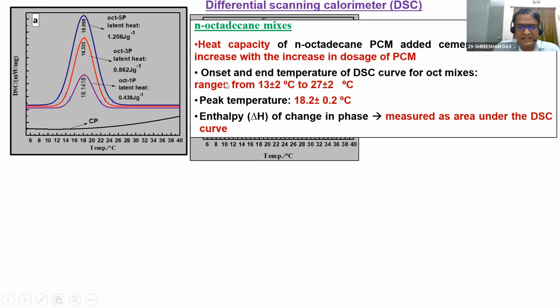Okay, and what is happening actually, the onset temperature of the DSC curve for the octadecane mixes started from 13 plus or minus 2 to 27 plus or minus 2, and the peak temperature is 18.2 plus or minus 0.2. You can see this is my peak temperature, and at this point the phase transition happens. So octadecane, the phase change material, will change its phase. But how? By absorbing the heat, and that's what is visible here. This peak is nothing but the signature of the heat absorbance.